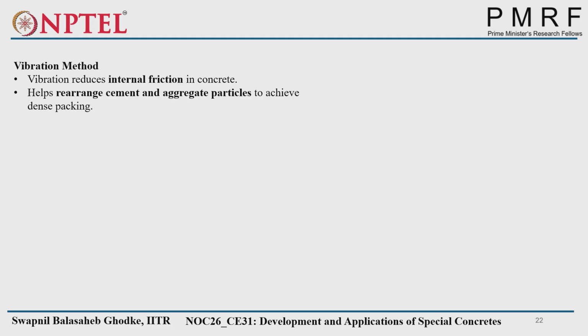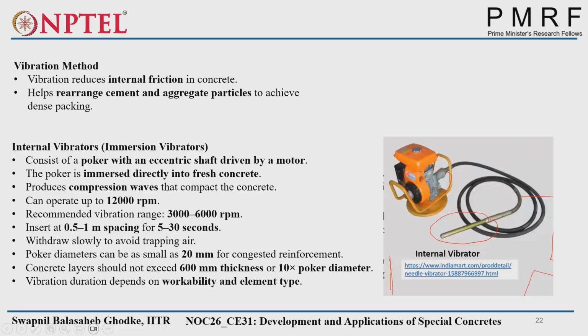Next is the vibration method. Vibration, through internal friction, rearranges cement and aggregate particles to achieve dense packing. The most commonly used vibrator on site is the poker vibrator. It consists of a poker with an eccentric shaft driven by a motor. The poker is immersed directly into the fresh concrete and creates compression waves in it. It can operate at 3,000 to 6,000 RPM, up to 12,000 RPM. The recommended insertion spacing is 0.5 to 1 meter. Suppose you have a long column or long slab: at 0.5 to 1 meter spacing you vibrate the concrete for 5 to 30 seconds. Withdraw slowly, both while inserting and withdrawing, to avoid trapping air.